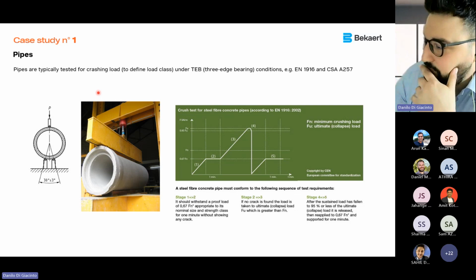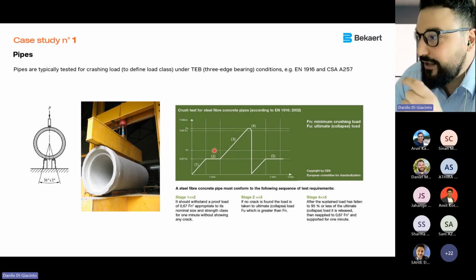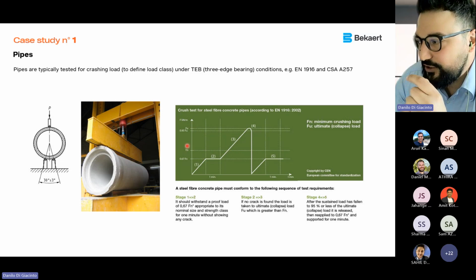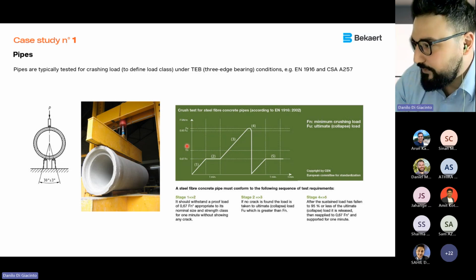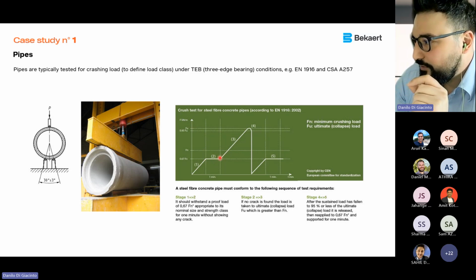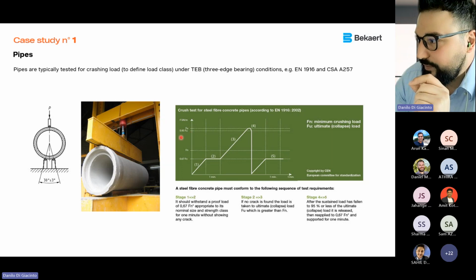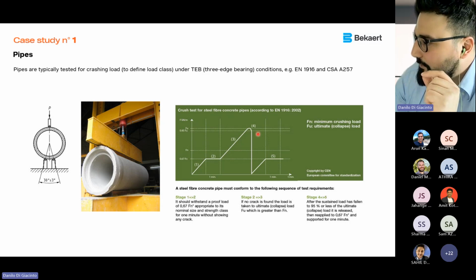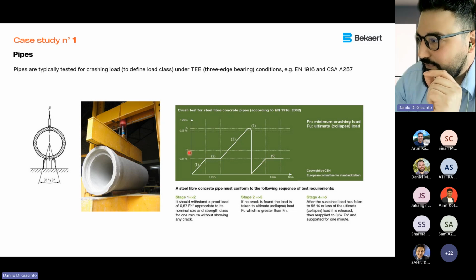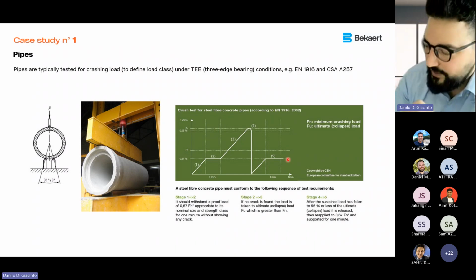And for steel fibers, you have to hold 67% of your design load, which is what you want to achieve to assign a specific load class to your pipe, for 1 minute without any cracks. Then you increase the load up to an ultimate load, which has to be higher than the design load, and to drop to zero, load again and withstand the same 67% of the design load for another minute. You can achieve that very easily.